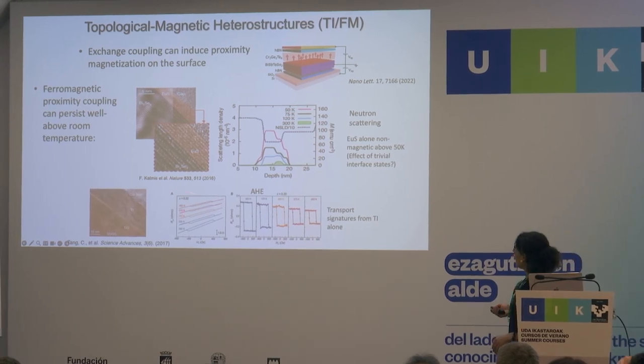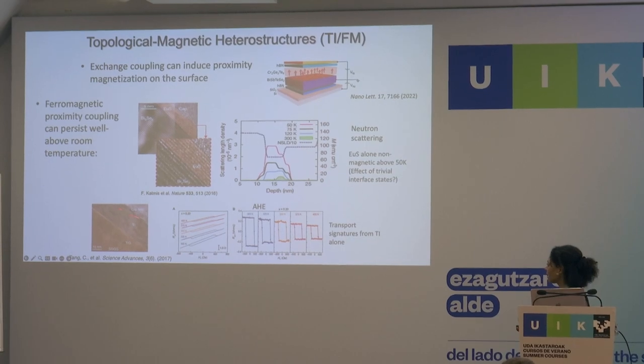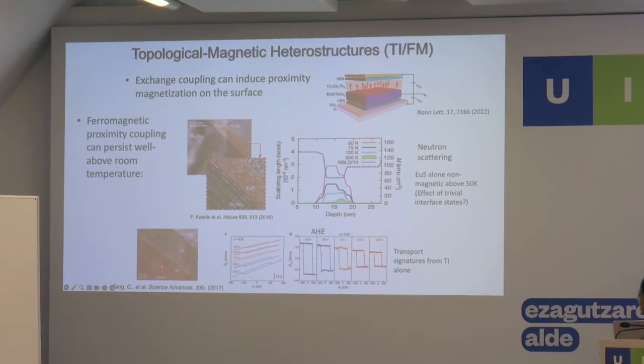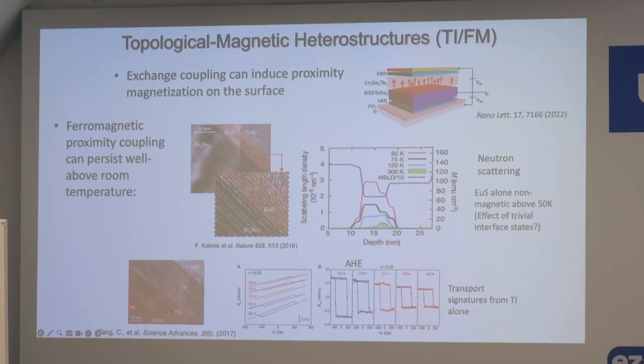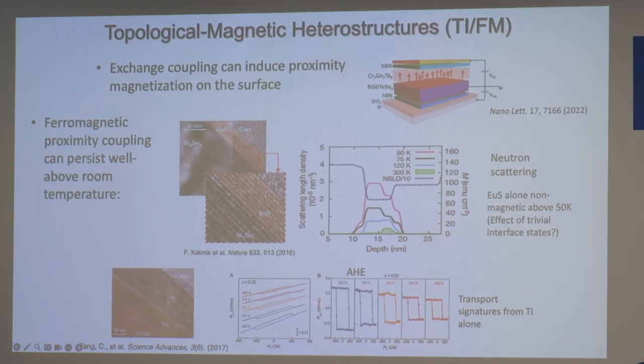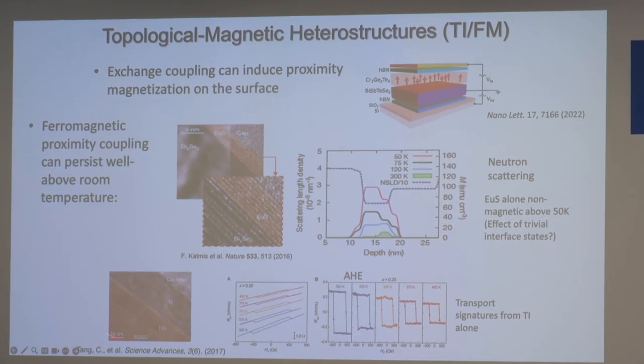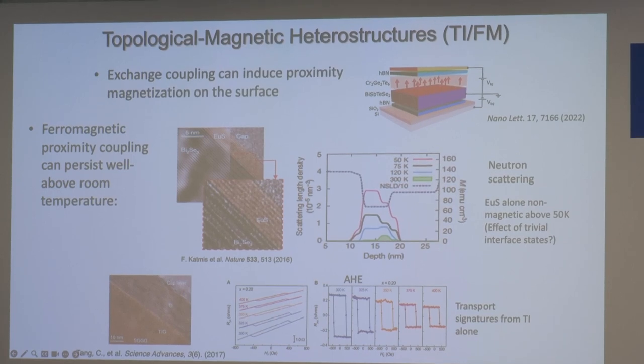There's another experiment, I think, that showed this even more clearly. This is a topological insulator and a magnetic insulator. And here you can see the anomalous Hall effect. And again, it's a magnetic insulator, so the magnetic material doesn't conduct. So when you measure things like the anomalous Hall effect, the only conduction is happening in the topological material. And so in this case, they measure the anomalous Hall effect where the transport signatures are from the TI alone. And you can see this anomalous Hall effect all the way up to 400 Kelvin. Okay, and that has to be just from the topological surface state and the proximity magnetization.